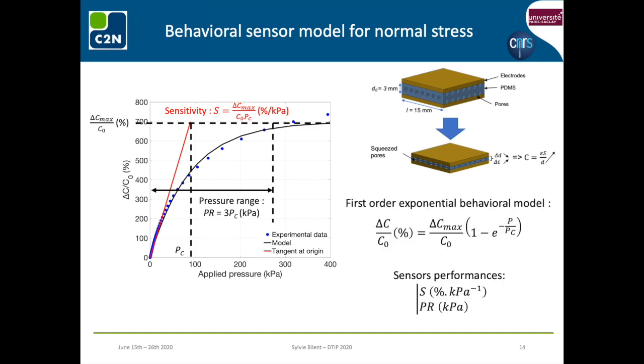In order to easily extract these performance parameters from sensor experimental responses, we'll build up a behavioral model which is presented here. This model links the observed capacitance change delta C to the applied pressure P through the first-order exponential expression in which C0 is the load-free capacitance, delta C max is the maximum capacitance change, and Pc is the characteristic pressure. A numerical fitting between the model and the data allows delta C max and Pc to be assessed, and consequently the sensitivity S and the pressure range PR to be estimated.